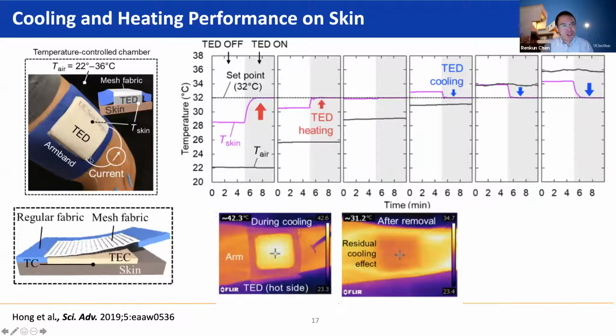And we did a small demo by integrating this device into a fabric and a coverlet on the arm. This is Zhang, the student's arm. And so you can see that we change air temperature from 22 to 36 degrees Celsius. So it's a wide range of air temperature. And without the TEC, so this part shows before the TEC is turned on, the skin temperature also changed, maybe from roughly 28 to 34 degrees Celsius. But of course, when you turn on the TEC, you can always achieve a target set point. In this case, the set point is 32 degrees Celsius.